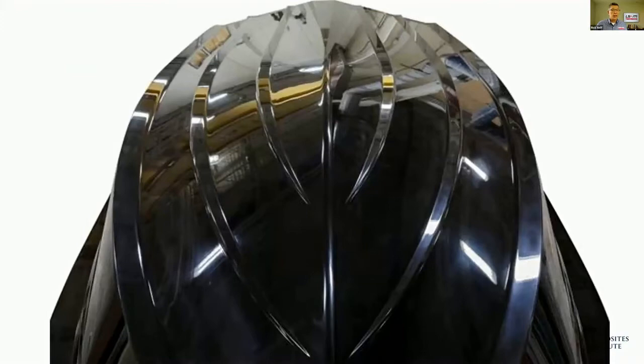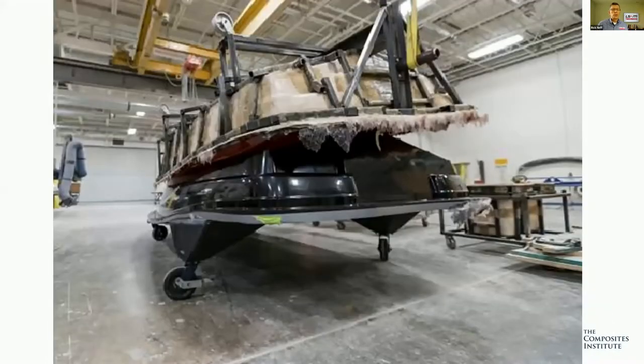And this looks just like the boat. And why would you want something that looks like the boat that's not a boat? Well, because we use that to actually make the molds that are used for production. So this plug is used to have a fiberglass mold made on top of it with the structure that's needed added to it. And the thing is they don't need just one mold. They need many molds because it's a very high production boat. So they can only make about one boat a day per mold. So depending on the number of boats per day they need to make, they need more molds. So this is a good way to do it.